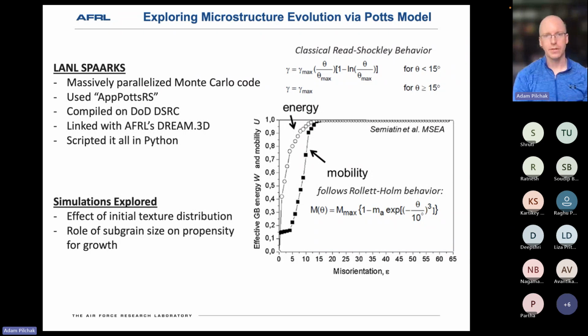This is a hugely parallel Monte Carlo code. It's got quite a bit of functionality and capability in terms of introducing different stored strains, grain boundary energy anisotropy, grain boundary plane anisotropy, multiple phases. Lots of capability in there. So we compiled that on one of the DoD supercomputers. I worked with a guy, Austin, who's now at Ohio State, that's a wizard with Python. So he scripted everything up so we could create digital microstructures within the DREAM.3D software suite, and then send them directly to the supercomputer and run some simulations where we were exploring the effect of the initial